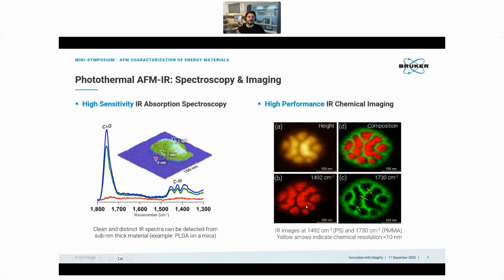Now you can switch the wave number on the same sample, same area. You do just a second scan by switching the wave number of the laser. Then in that case, it's the one corresponding to PMMA, 1730 centimeter minus 1. And then suddenly you see that the contrast of absorption totally changes, because only now the areas with PMMA are the ones that are absorbing. And these arrows here are meant to show you the resolution of these changes in the chemistry mapping. We are around or even better than 10 nanometer.